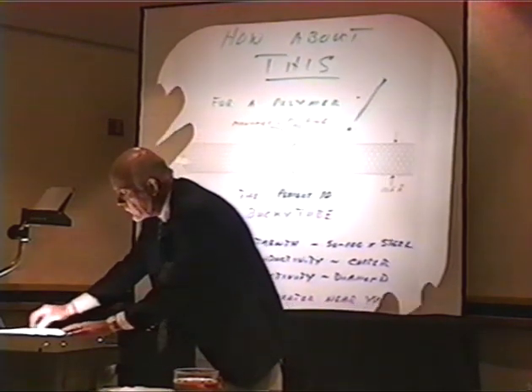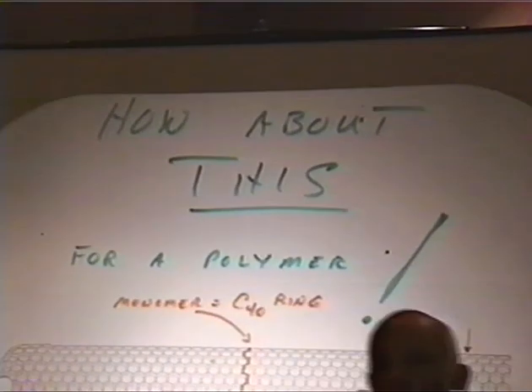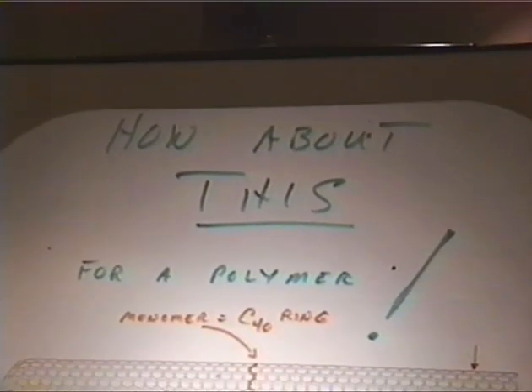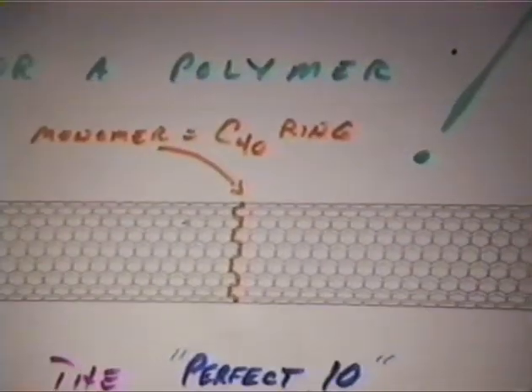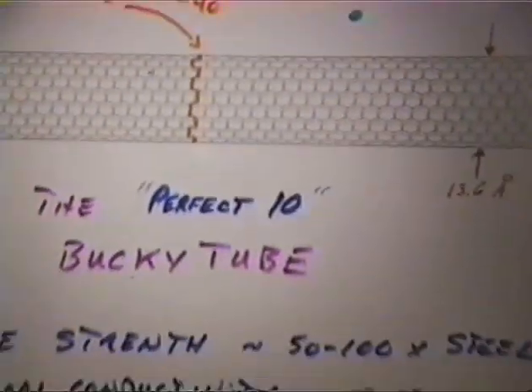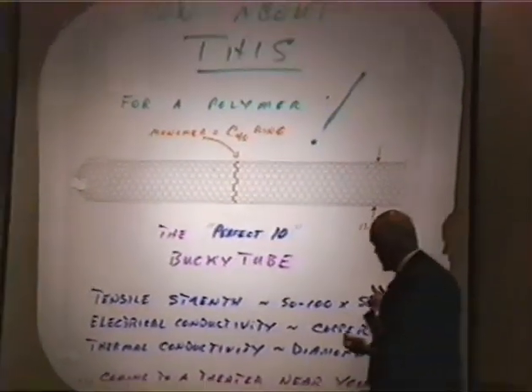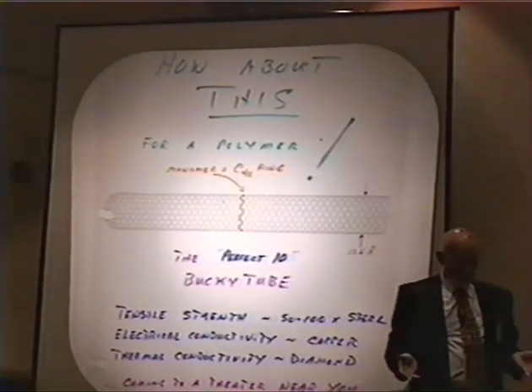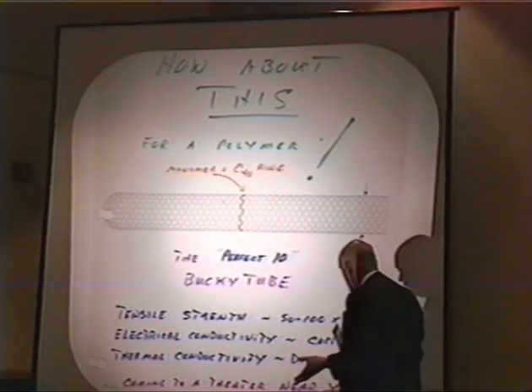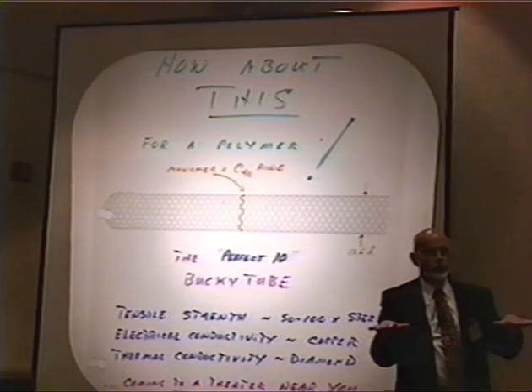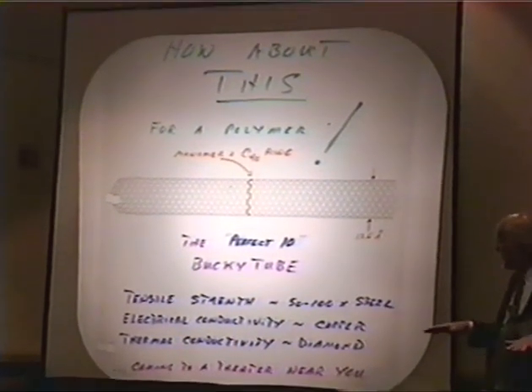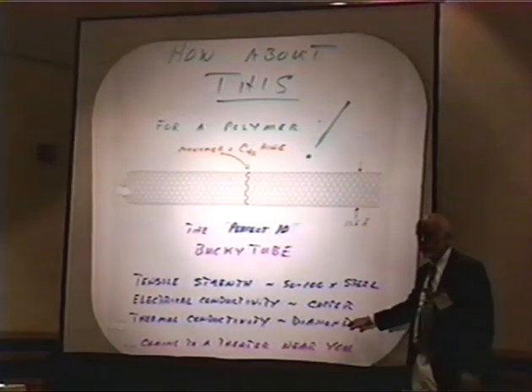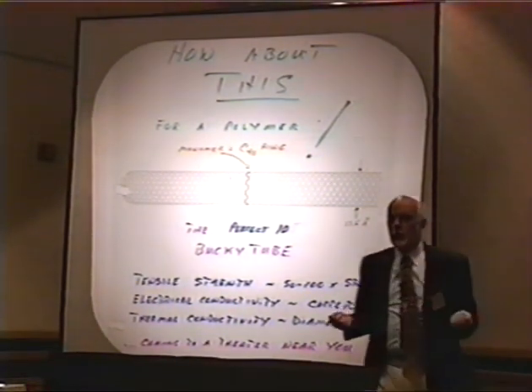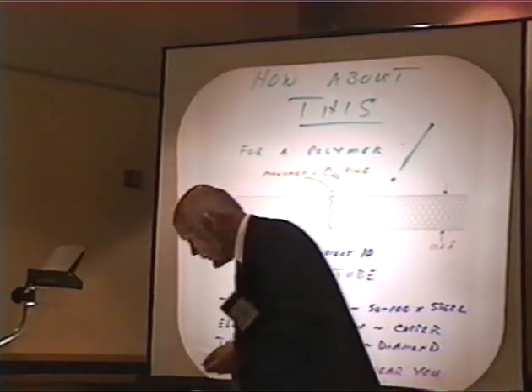So, that being the case, perhaps instead of thinking of this as a single crystal of carbon, we should think of it as a new polymer. It's made out of carbon. The monomer is either carbon atoms, or if you prefer, this ring of 40 carbon atoms around the unit cell. Tremendous tensile strength, electrical conductivity, maybe upwards and competitive with copper, for all we know might be better. Thermal conductivity, inherited from that of the graphene sheet and HOPG or crystalline graphite, may be rivaling that of diamond. This would be a tremendous engineering polymer if we were able to make this.